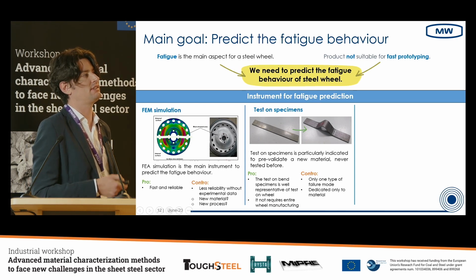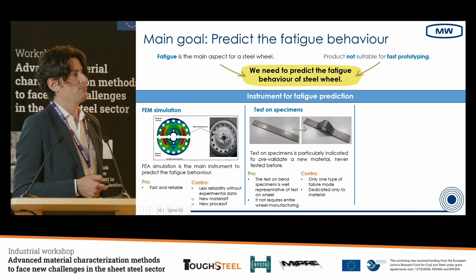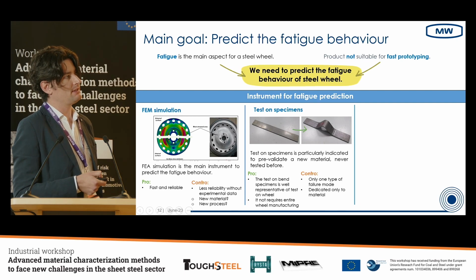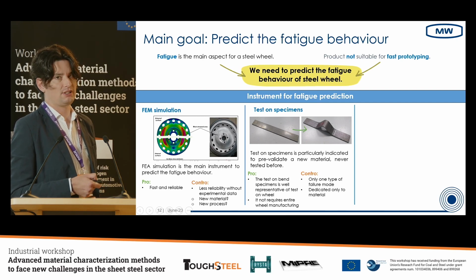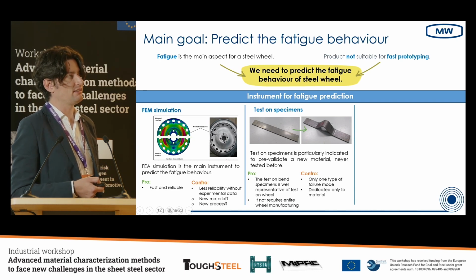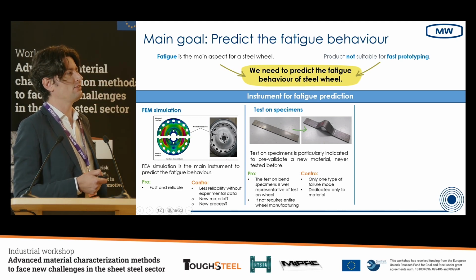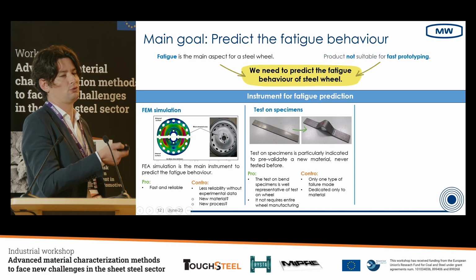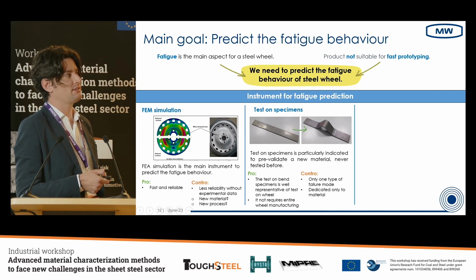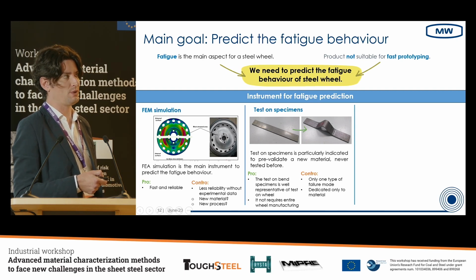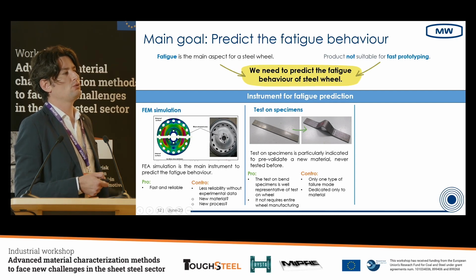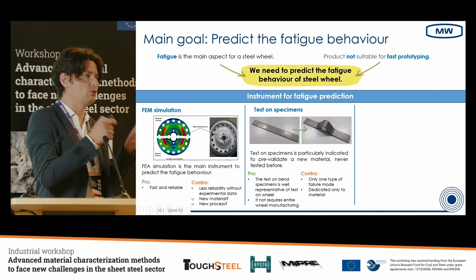This is the second instrument. It is a test on a specimen, in which we bend the flat specimen, so we can introduce the hardening phenomena during the stamping, and we can convert the pure traction and compression forces into bending forces, similar to what happens in the bending test. The pro is that the test on specimen is well representative of the test on the wheel, and does not require the wheel manufacturing, so we can do it before creating the wheel. The contra is that this type of test has only one failure mode, always the same, in the same position, and is dedicated to the material, not to the entire component that is composed of 2 different components with the welding and so on.